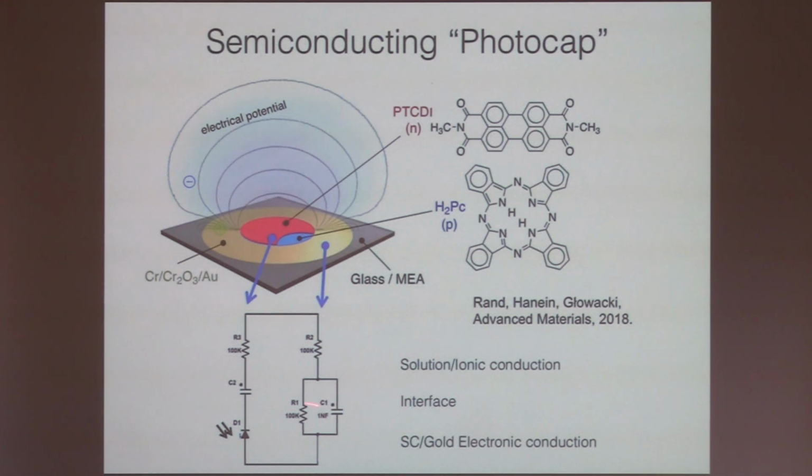So here, again, it's modeled crudely as a double layer capacitor with a parallel resistor representing gold. Without this material, if the film is covering the entire surface here, this one here would be a very large load, and the voltages that we can build diminish very, very quickly.